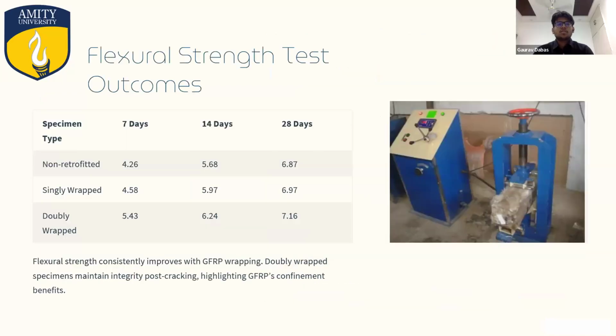Now, our third and final test, the flexural strength test. The flexural strength also increased across all curing periods. The doubly wrapped specimens peaked at 7.16 MPa compared to 6.87 MPa for control samples. More importantly, GFRP helped maintain structural integrity even after cracking, delaying the total failure of the concrete.